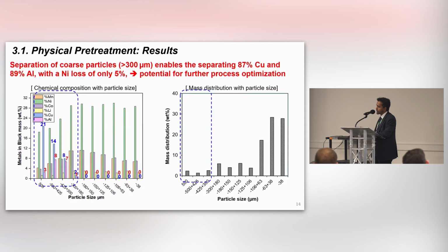In order to understand more about the chemistry here, we conducted some chemical composition analysis. Based on this, we identified that between 500 and 300 micrometers we observe lots of copper and also aluminum. And if you see the mass distribution, the mass fraction between 500 and 300 micrometers is very low, less than 10%. If we separate the coarse particles over 300 micrometers, we can separate 87% of copper and 89% of aluminum, with nickel loss of only 5%. So there's some potential for our future process optimization to remove those copper and aluminum before applying any hydrometallurgical process.